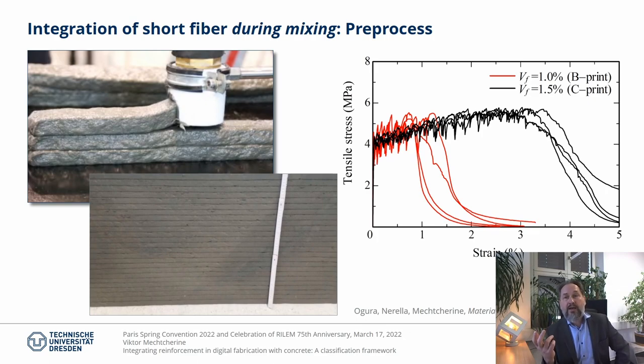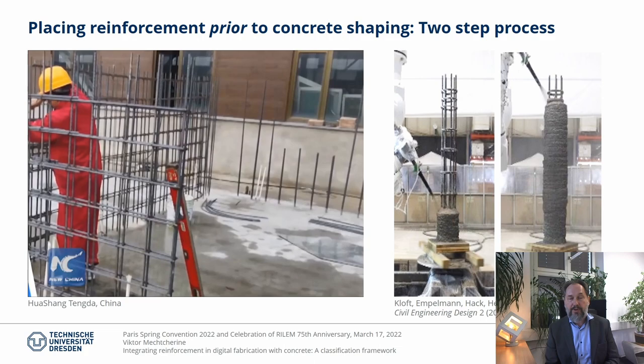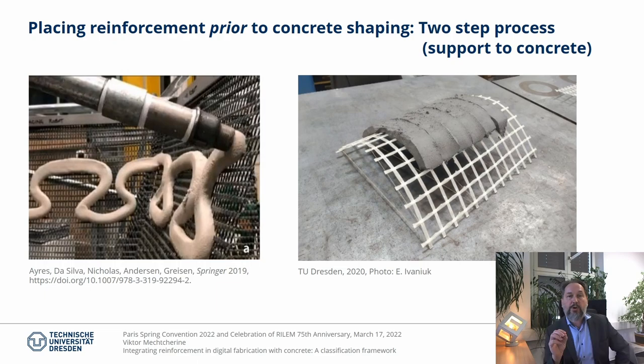By using a comprehensive material design, we can attain a ductile strain-hardening behavior for such printed materials when subject to uniaxial tension. This material concept was recently successfully used by our partner Shimizu Corporation in Japan for fabrication of integrated formwork for bridge support. Another option is to place reinforcement prior to concrete shaping. In these cases, reinforcement is encased with concrete in an additive process, while it doesn't provide any substantial support to fresh concrete. In contrast, in these other examples, reinforcement provides support to concrete, and the concrete shaping process is a formative one, since the shape of the element is defined by the supporting reinforcement. Obviously, we have two fabrication steps here: first reinforcement, then concrete.